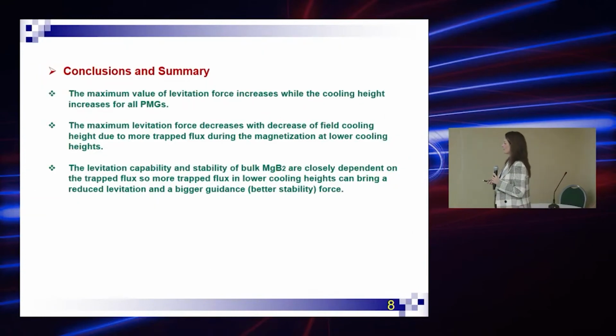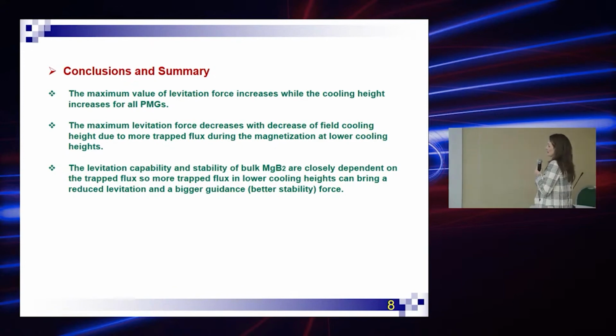In summary, the maximum value of levitation force increases while cooling height increases for all PMG arrangements. The maximum levitation force decreases with decrease of field cooling height due to more trapped flux during the magnetization process at lower cooling heights, and the levitation force and stability of bulk MgB2 are closely dependent on this trapped flux. So more flux at lower cooling heights can bring a reduced levitation force and a bigger guidance or better stability. It is very important as magnetic levitation force.